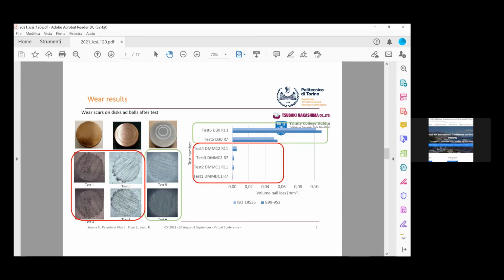However, this can be explained by considering the higher surface roughness of the DMMC specimen 2, which, as proven by experimental observation, can counterbalance the effect of increasing the contact speed. For D30 and DMMC specimen 2, higher linear local speed results seem to be related to a higher abraded volume for both coatings.